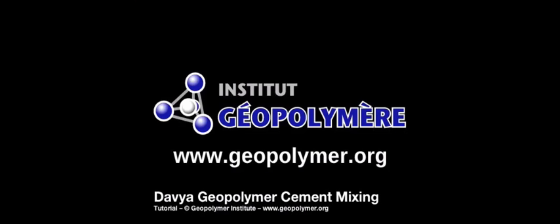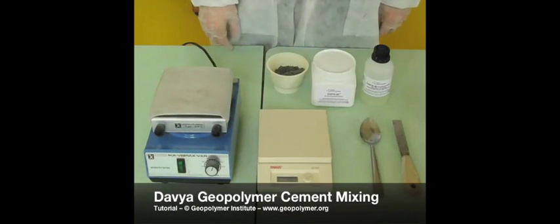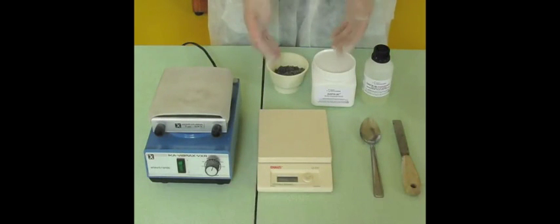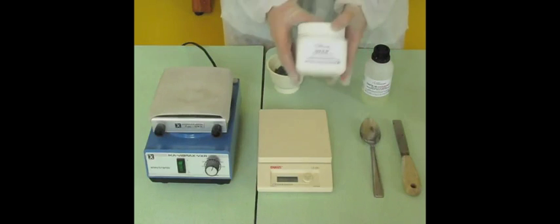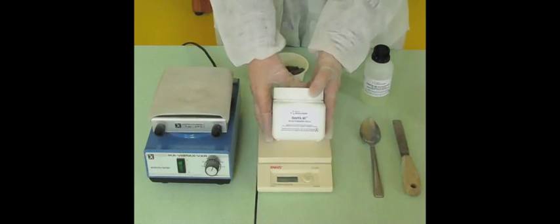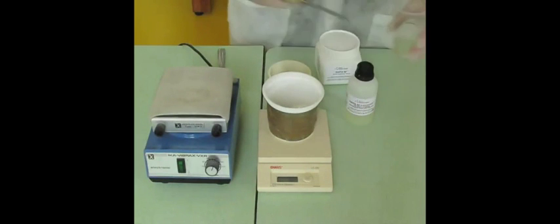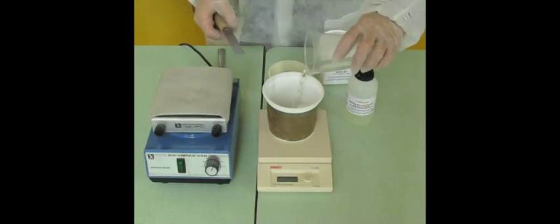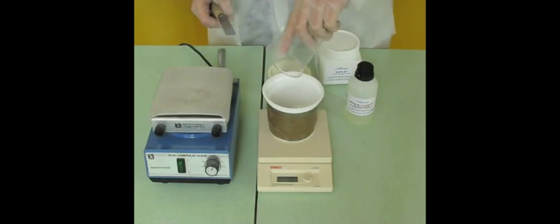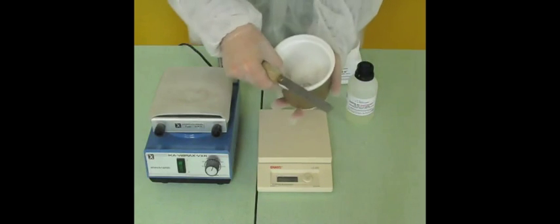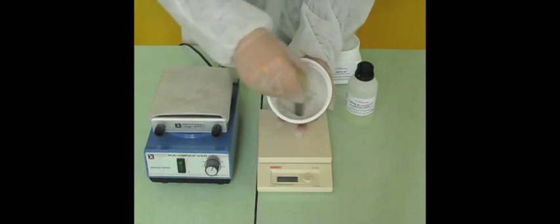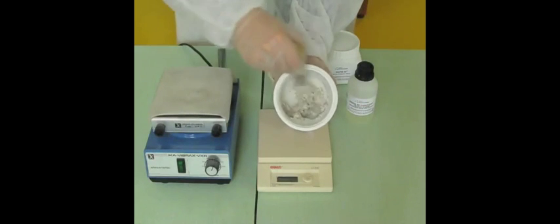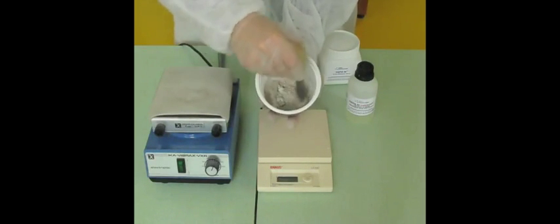So now I show you how we make a geopolymer cement. This is totally different. We master exactly, we know what we do. The Davya tutorial describes the manufacture of a high-strength cement. We show here the easiest method to do it. Pour the hardener into the powder. Mix the whole with a mixer or by hand until obtaining a fluid resin. Do not add water.